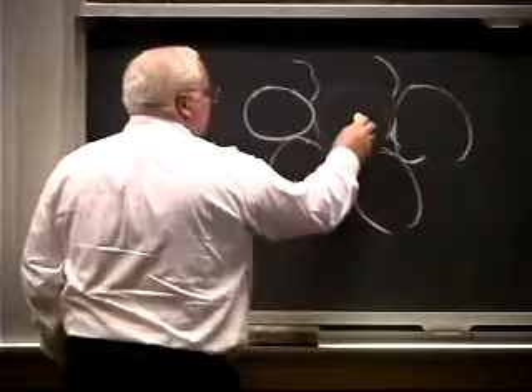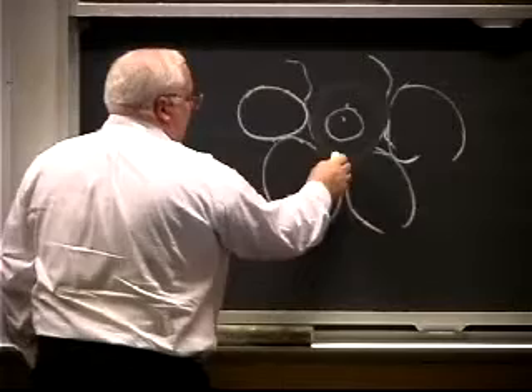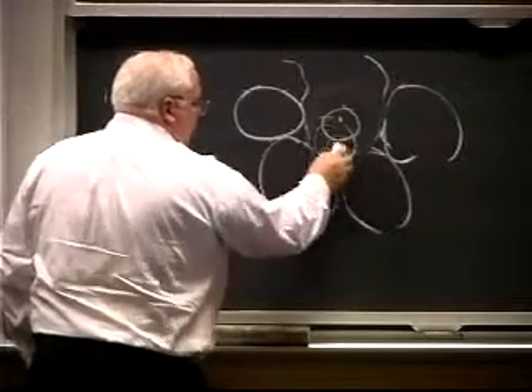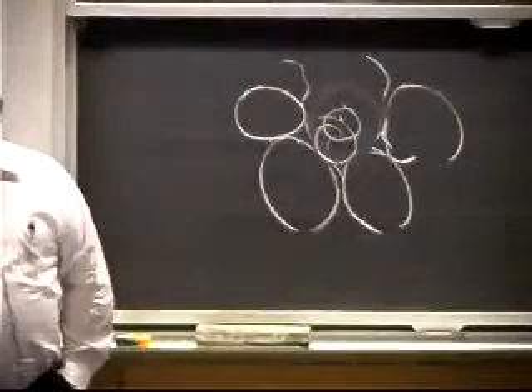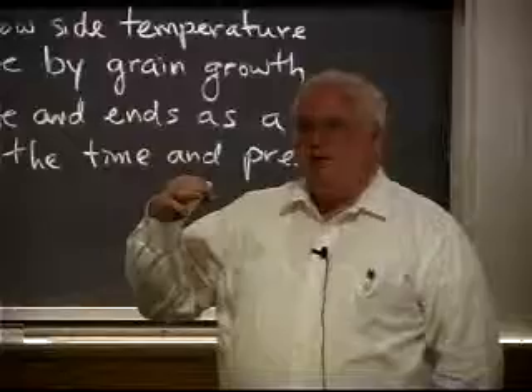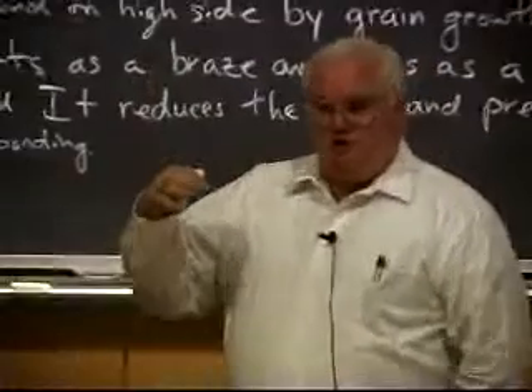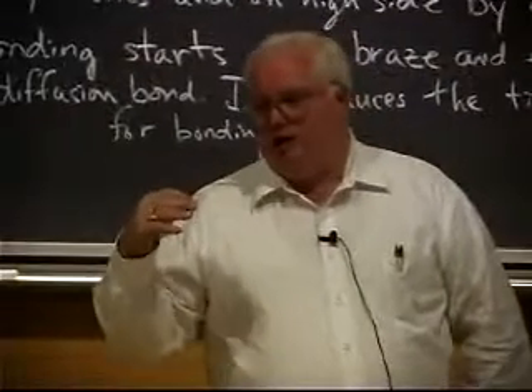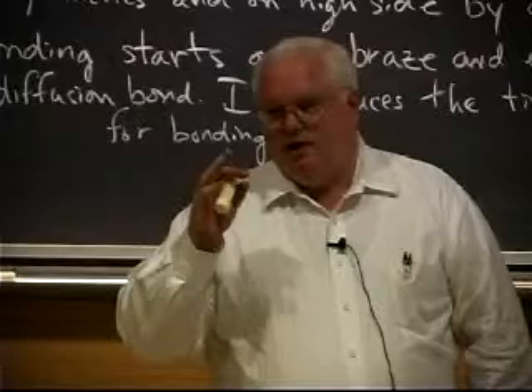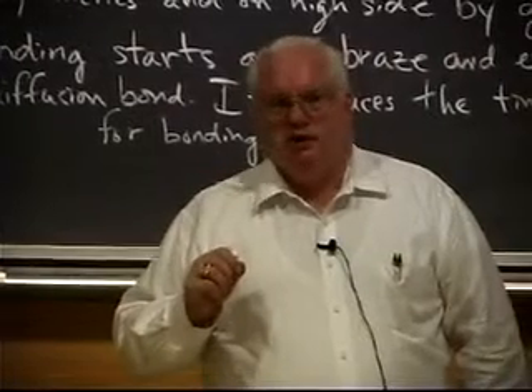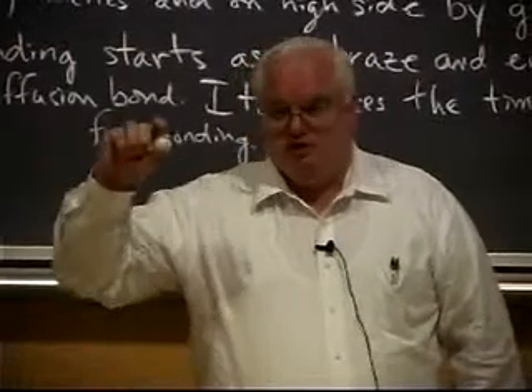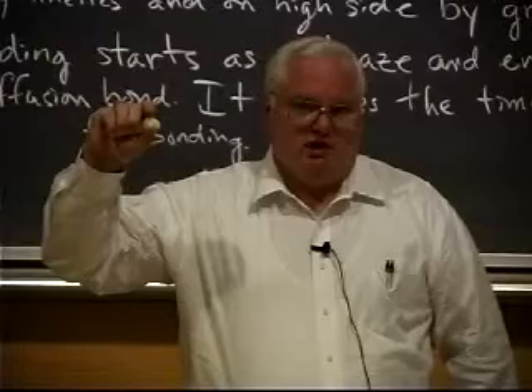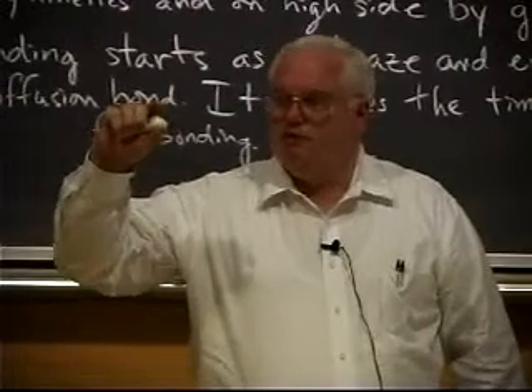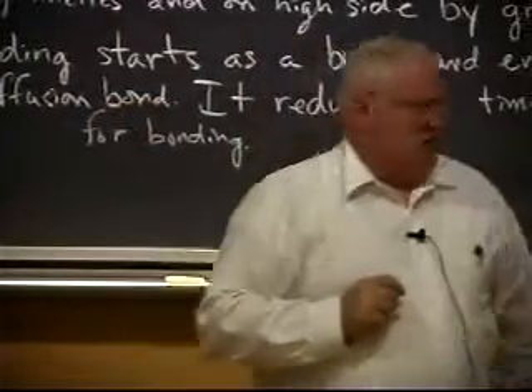The liquid erosion is very rapid, and as this copper particle gets smaller, it basically falls down in between these other particles and it blocks the pores. And so you're only able to typically infiltrate maybe a half a millimeter or a millimeter. But that's infiltrated 1.5 centimeters in that particular case, mostly because he was just limited. It started out maybe 2.5 or 3 centimeters thick, and he squeezed it down to make that.